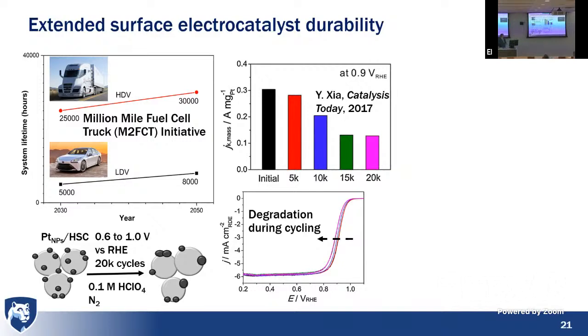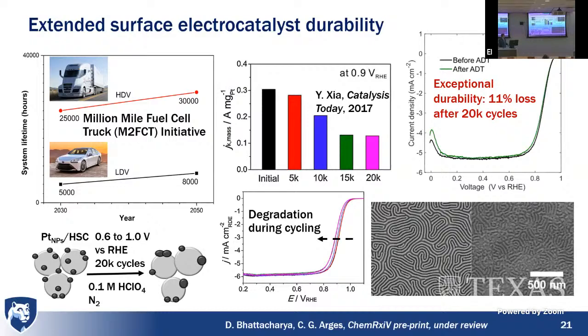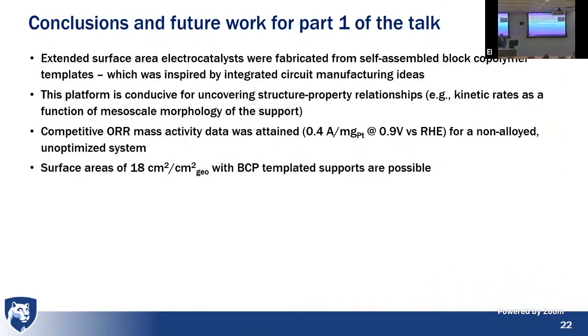And so we ran a very identical or similar, I believe, same potential. We started from 0.6 to 1.0 volt, but same number of cycles, same conditions. We only saw 11% loss in our mass activity, not over 50%. And then our structure before and after, more or less the same. So we were very happy. We were impressed with this data. And so there's a lot of room to go.